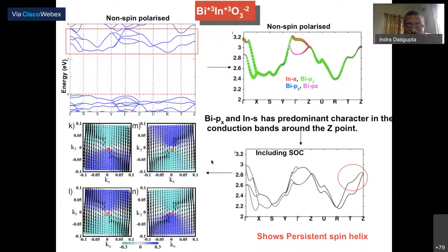Now I'm going to touch upon another compound, which is BiInO3. If I do a similar calculation, I find that the spin texture is a persistent spin texture, again in the conduction band, again at the Z point. So I look at the Z point and the spin textures around it. For this compound, although it has similar symmetry to my LaWN3, it has a different kind of spin texture. But the thing to point out here is that the conduction band which sustains this spin texture has a character of bismuth px and indium s.